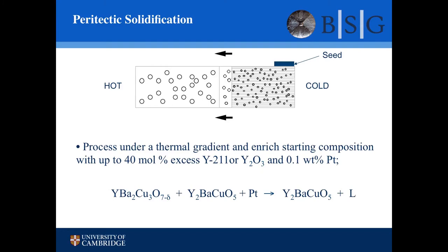Here's our superconductor. We've got a hot end and a cold end. So this is probably at about 1,005 degrees. We put a seed at one end. The hot end that's decomposed, the white background is liquid. The circles are our second solid 211 phase. Two things are happening here. We need the rare earth ion or yttrium to grow our 123 phase. So at the growth front, we're dissolving our 211 phase, and that's happening at a certain rate, and we're growing at a certain rate from right to left.